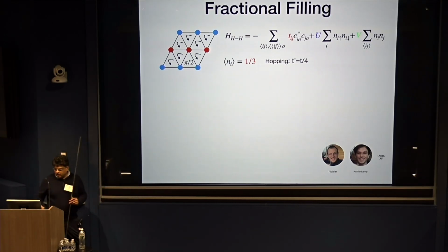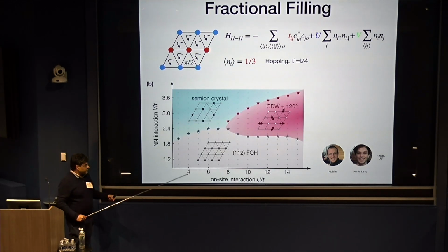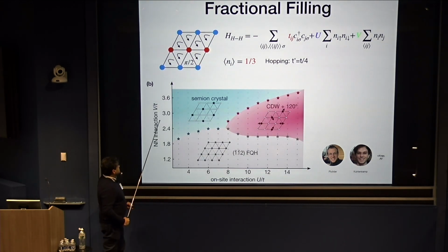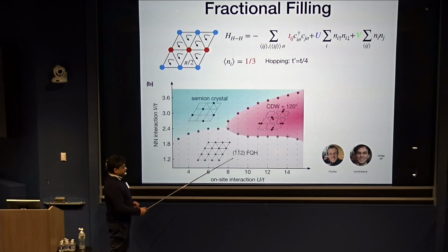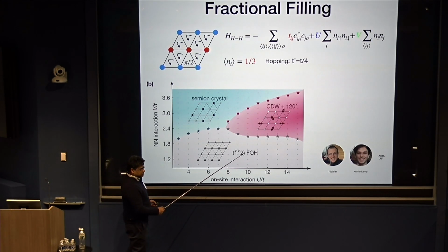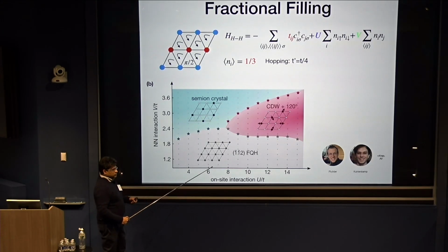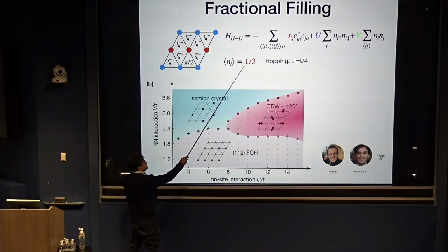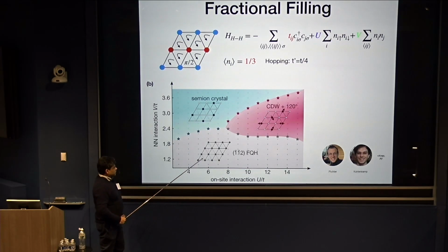Now what they saw is that if you look at this phase diagram as a function of U over t and this interaction V, the neighboring interaction, amazingly, you find this phase, which is a fractionally filled Chern band, which gives you the fractional quantum Hall effect, the fractional Chern insulator, if you like. This is what you'd expect if you fill a Chern band with filling two-thirds, because you have two sites in the unit cell, so you double this over here. But what's even more interesting is that when you change interactions, you get two other phases.